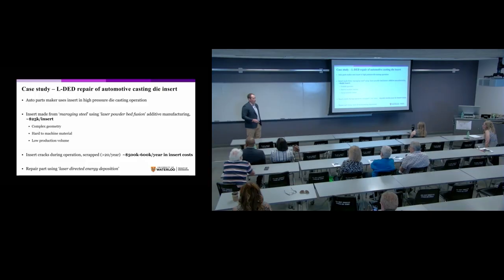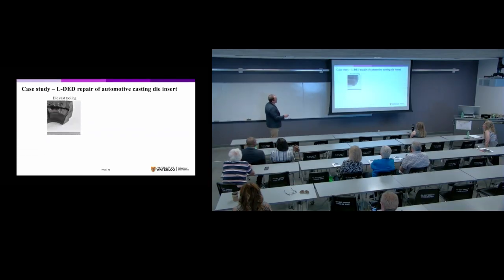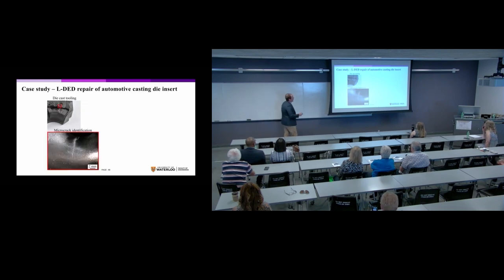So here we can see a segment of this piece of tooling. We can't show the full thing, but this is a segment of the tooling. Again, it's about a foot long, weighs about 40 pounds, made out of steel. And when we zoom in on this little area here, we can see the crack that they're talking about. This crack is what's causing them to scrap this component. If we look at the scale bar here, the width of this crack is far less than 1 millimeter wide. But it's enough that once it forms, they have to get rid of it.